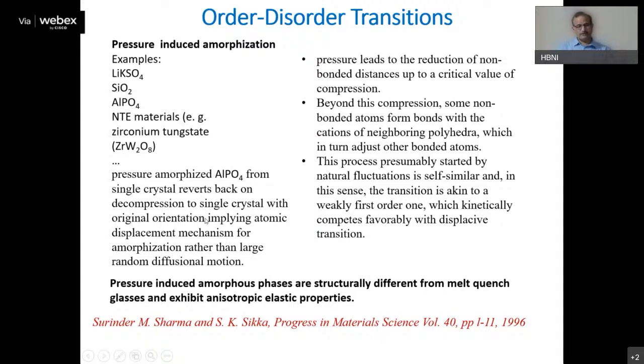And there is one more inference that we can draw from this: the disordered or amorphous phase under pressure, like amorphization under pressure, should not be thought of as similar to a melt-quench phase. Because if the phase is melt-quenched, like a glass phase, you have isotropic physical properties. Whereas it has been seen that if you take the amorphous phase, which is amorphized after pressure cycling, you get anisotropic elastic properties, which clearly indicates that this pressure-induced amorphous phase should not be considered equivalent to the melt-quench phase.